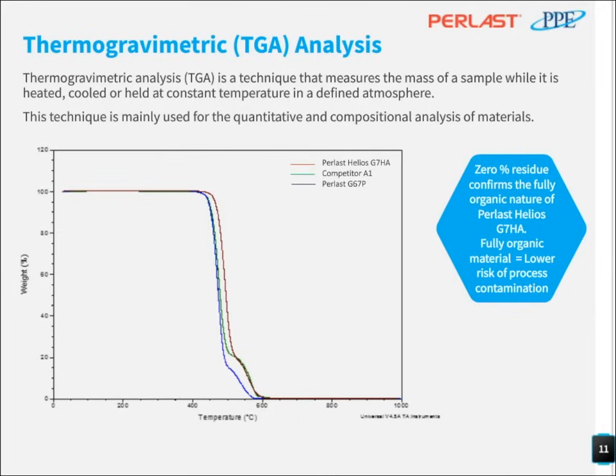If the material is fully organic, there will be no residue left after the test. If the material is inorganically filled, then as the inorganic fillers are stable at temperatures over 1000 degrees Celsius, we will observe some residue after the test.